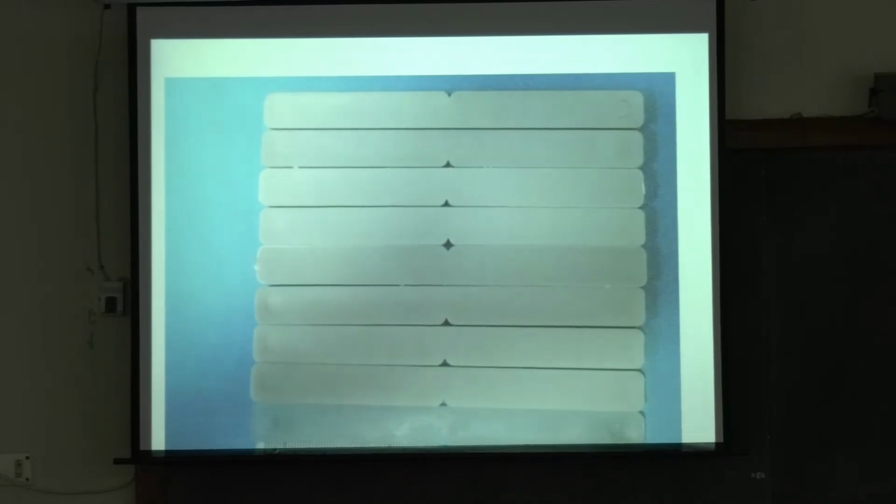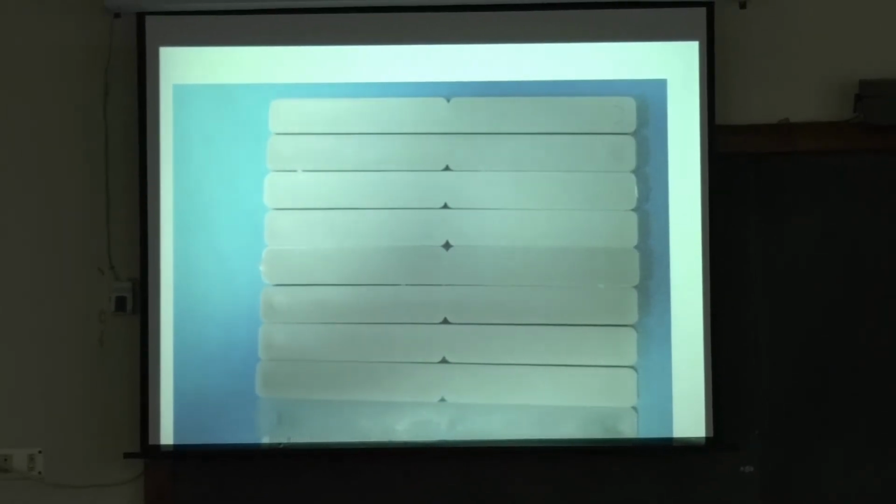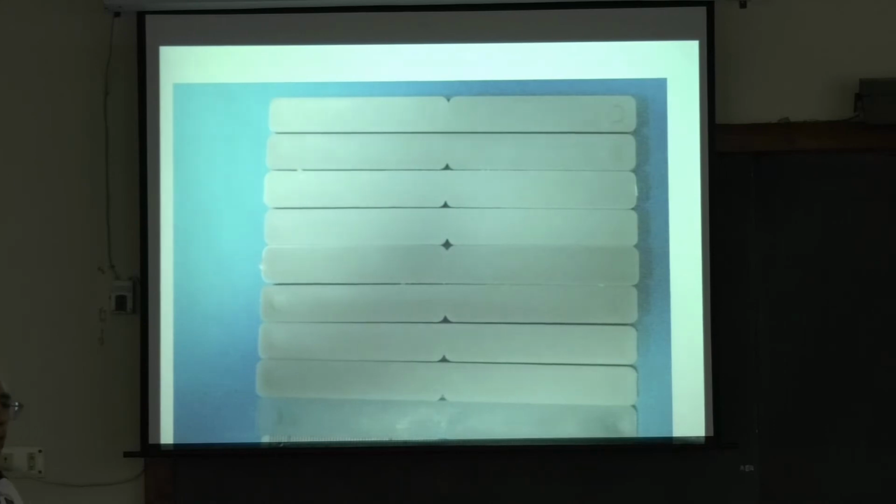But now they all look the same white. Which means when you transfer the color of the fly ash, you don't always have to go for a very high percentage. Whether you take 5, 10, 15, 20, it all gives you very good whiteness. All right?